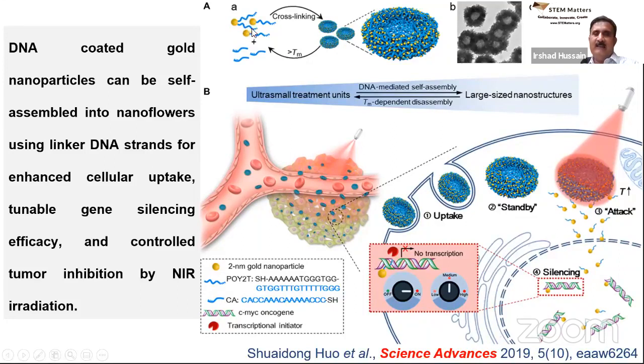And even more recently, this has been done, for example, by functionalizing gold nanoparticles with DNA initially, and then adding cross-linking DNA to make gold nanoflowers. And these gold nanoflowers can again be used for the delivery of siRNA to the cells. And then again, you can control the surface chemistry of these nanoflowers so that they are delivered to the region where they are desired.